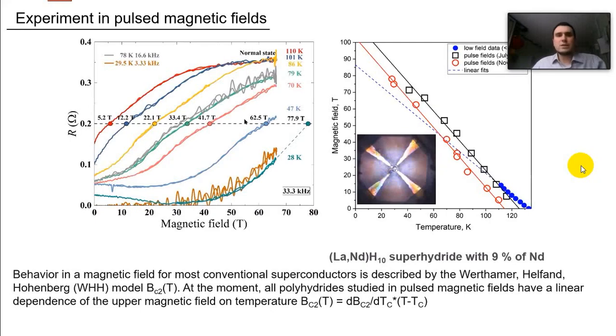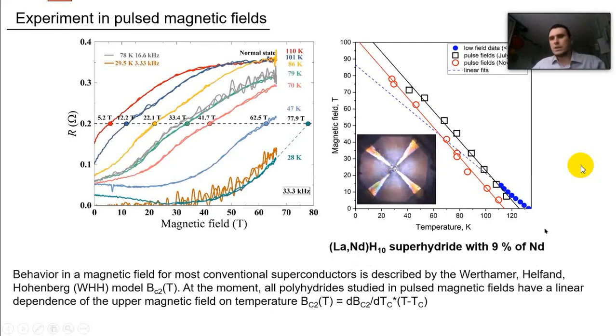Okay, these are two pictures of typical results that we can get in this laboratory in Dresden. We could reach magnetic fields experimentally. We could reach about 65 Tesla in pulse. It's a very high magnetic field, almost the maximum for diamond anvil cells. Extrapolated data, I showed a couple of circles for extrapolated data. It's up to 75 Tesla approximately.